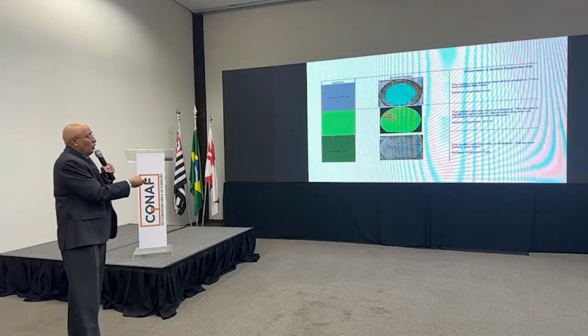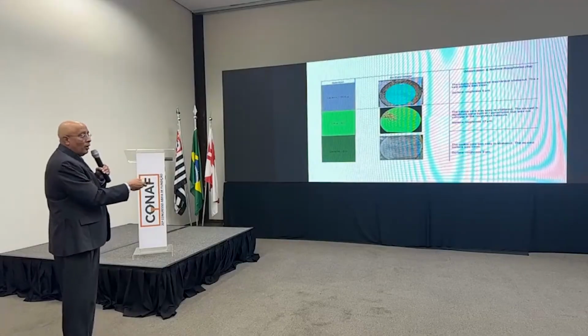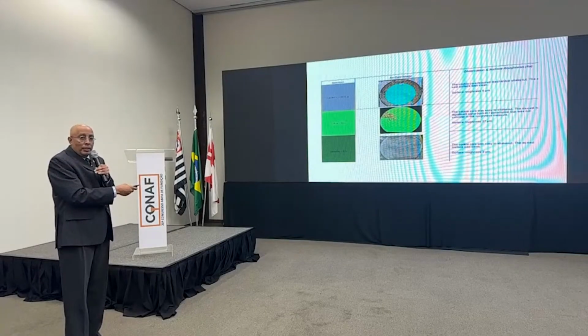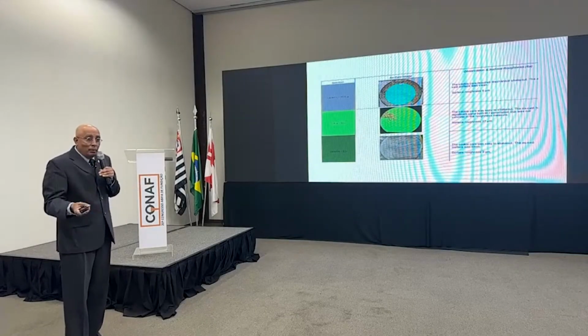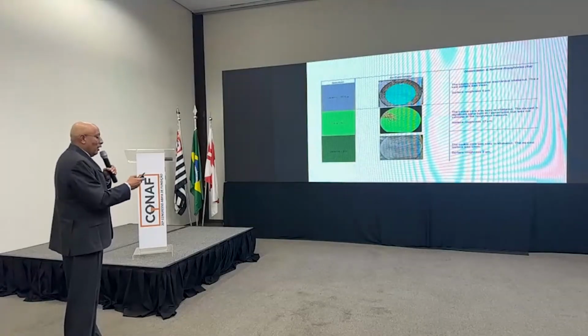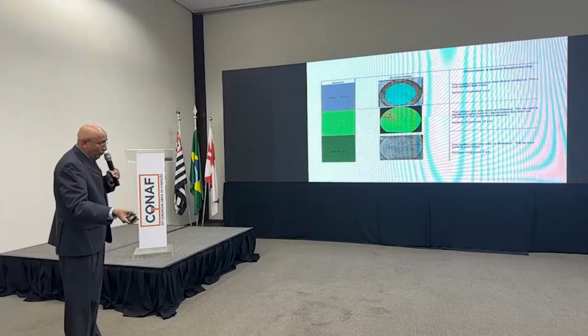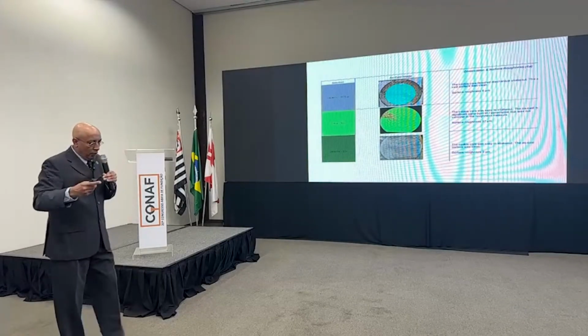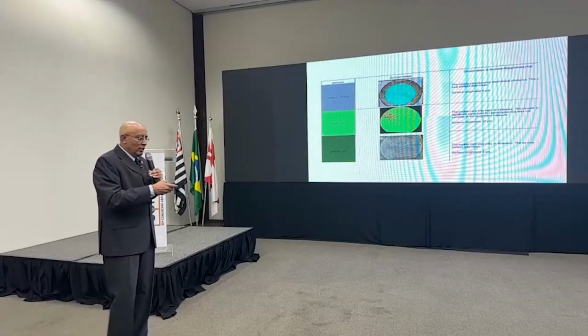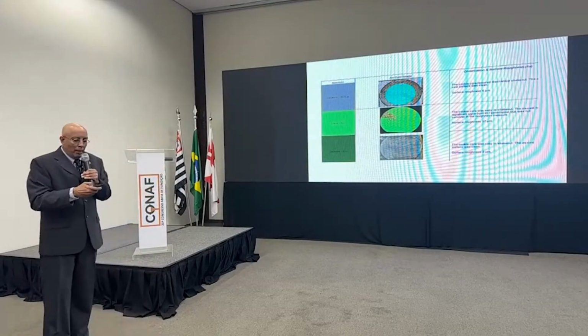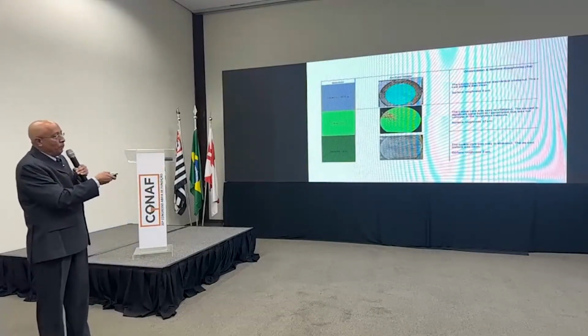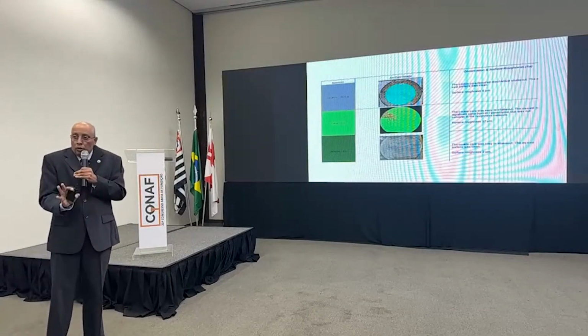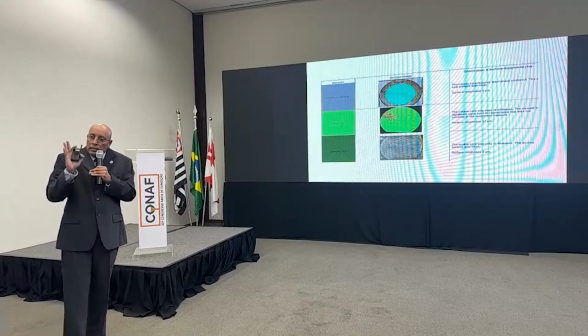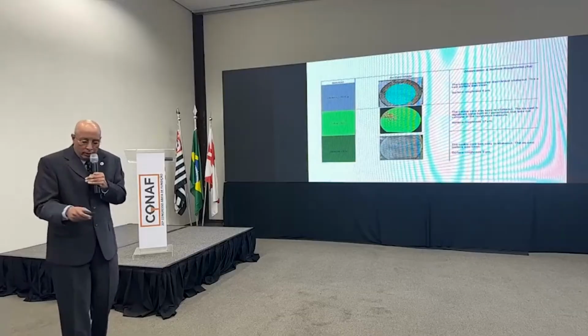In this case, you cannot afford this defect. Why? The mold in 3D printing is more expensive than the metal. So in this case, again, regardless, 3D printing or conventional process, you do not want these defects. The reason that I'm pointing out specifically, this is a penetration. We know this is not erosion. And that's why I'm telling you it's a 2 o'clock, 10 o'clock defect.